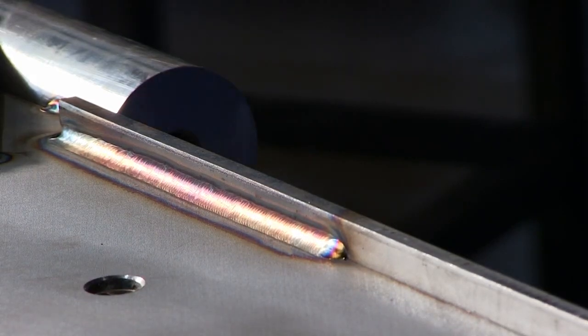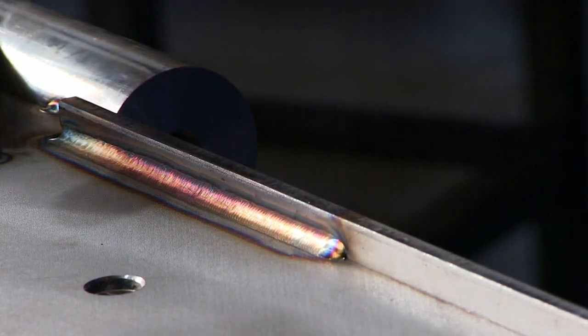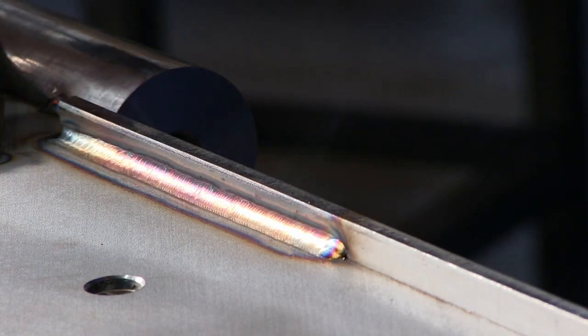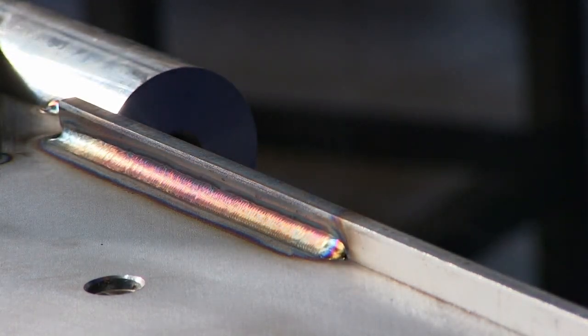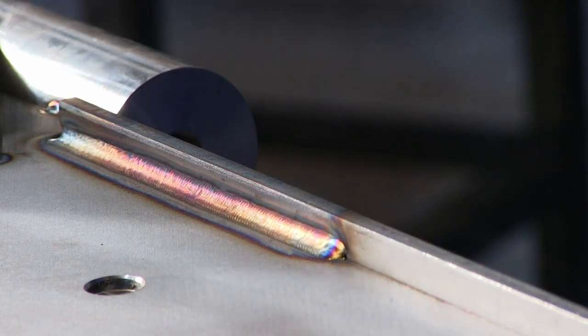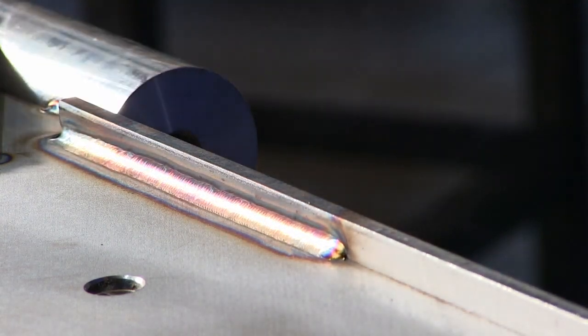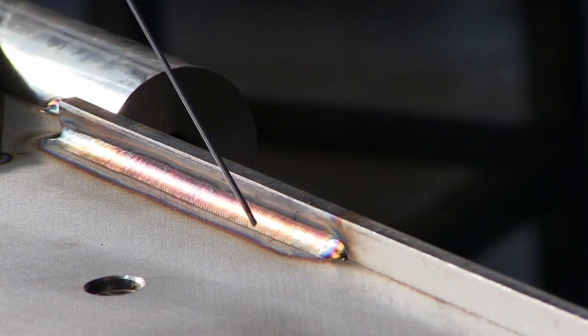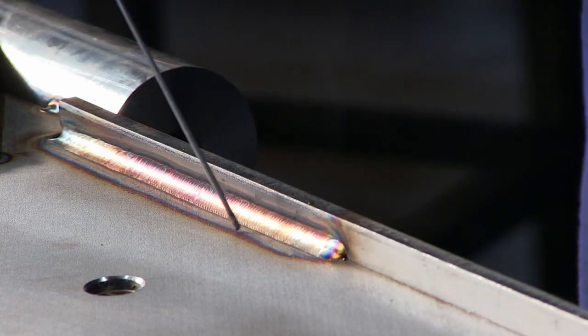a relatively nice and creamy weld, simply because of how everything is run during this weld. Obviously my hand is closing up a little bit, but you can still see the arc, and you can see the finished result in it. As I mentioned, because everything is very fluid in the puddle, you end up with a very smooth welding bead. So I'll just try to cover the light a little bit with my hand, because it's quite difficult to film on stainless steel.